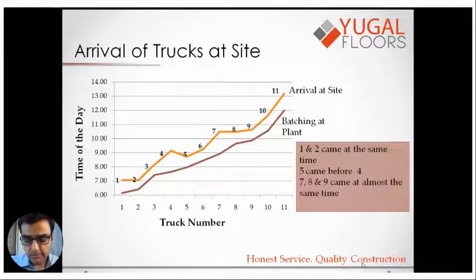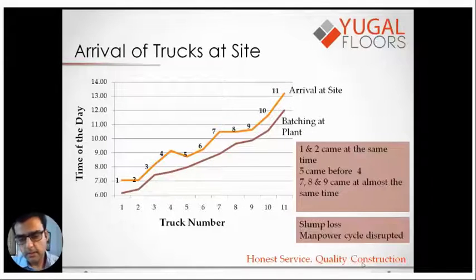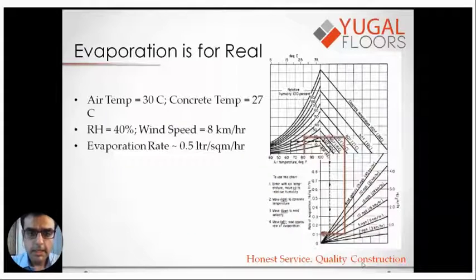Now, what implications does this have to me as a flooring contractor? It's obvious. Some of the trucks would lose slump because they are coming much later to the site than planned, and my manpower cycle is obviously disrupted again. And the third and the final variable is evaporation. On the right is a nomograph published by the American Concrete Institute. Dr. Wish also talked about this. I won't go into the calculations, but I have assumed an air temperature of 30 degrees Celsius, concrete temperature of 27 degrees Celsius, relative humidity of 40%, and wind speed of 8 kilometers per hour. What it means is my evaporation rate is about half a liter per square meter per hour.